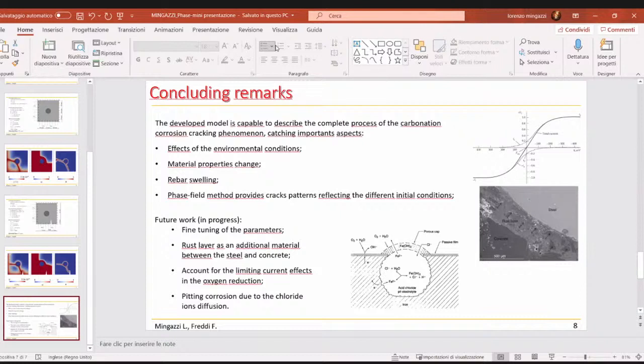To apply a coating on the bars itself, or apply a coating on the finished reinforced concrete? I would say on the concrete, mainly because applying coating to the bar may affect the bonding between the concrete and the bars, and that could lead to a loss of bonding between the two materials, which could be even more dangerous for the structural elements. But that's just my guess. I didn't investigate that aspect of this problem because I focus more on the numerical part.